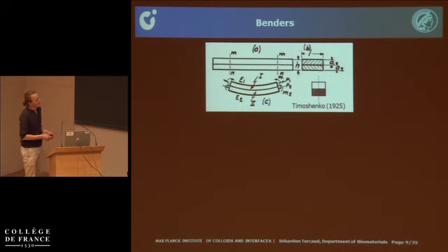So here again, this bilayer idea. It's really old. I think it was invented by a Swiss clockmaker even before that. But the first scientific paper about it is from Timoshenko almost 100 years ago. If you have a differential expansion in the cross section between the black, which wants to swell, and the white one that is just passively resisting, then you will have creation of curvature.